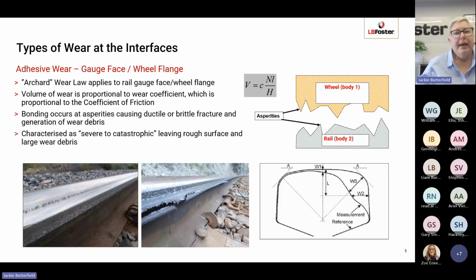So how this mechanism works is that the wheel and the rail surfaces are relatively rough, as you can see on the stylized diagram there. So we have peaks on the surface of the wheel and the rail, which are known as asperities. And in adhesive wear, under the force and the heat and the friction in the wheel-rail interface, these asperities or peaks actually touch each other and then they bond and weld to each other. So you're having, on a microscopic scale, the wheel and the rail bonding to each other.